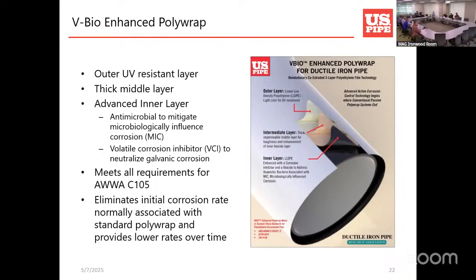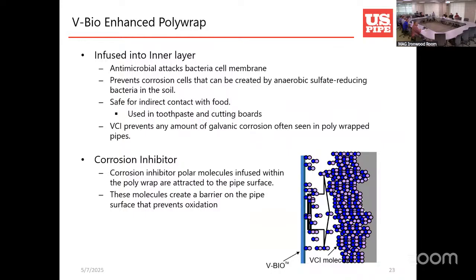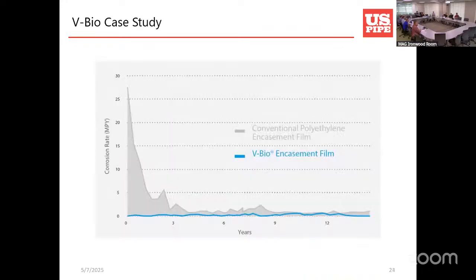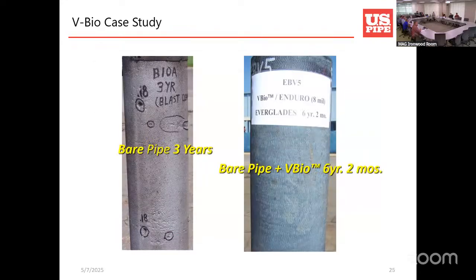Next slide. And that's what you see right there, the corrosion inhibitor. The polar molecules in that actually are attracted to the pipe surface, so it prevents that initial corrosion rate from occurring. Next slide. And this was from a DIPRA case study, and you can see it took a couple years for that corrosion potential to deplete, and that's as that oxygen level is depleting, so is the corrosion potential. But with that V-Bio from day one, with that corrosion inhibitor on there, it's protecting the pipe. Next slide. And then that's just a case study showing you how effective V-Bio is. And this was down in the Everglades, which is one of the most corrosive environments in the United States. So you can see how effective the V-Bio tool is.